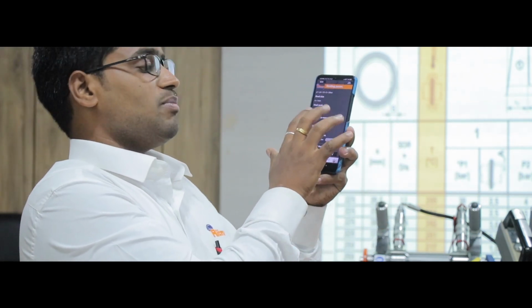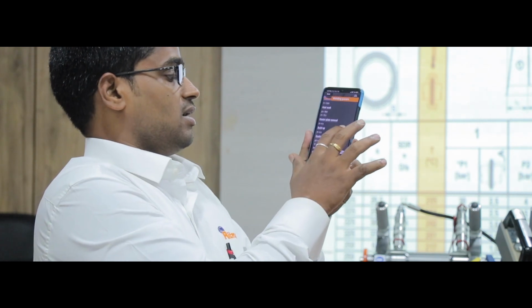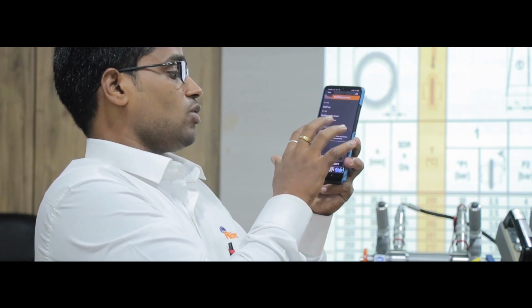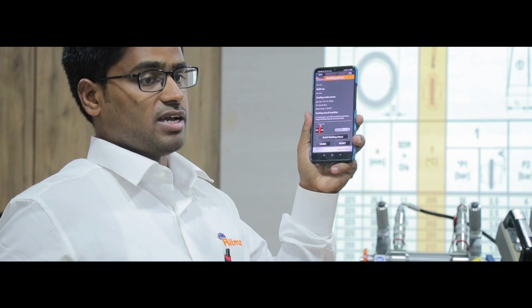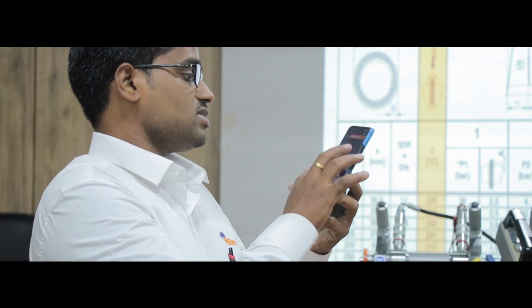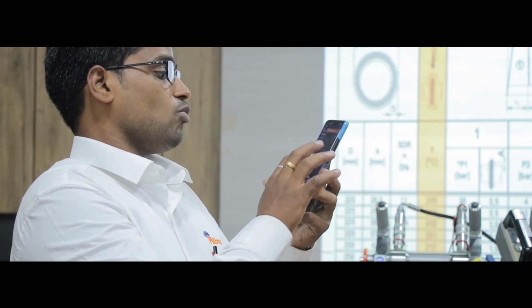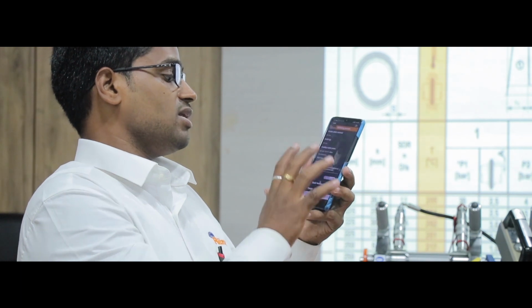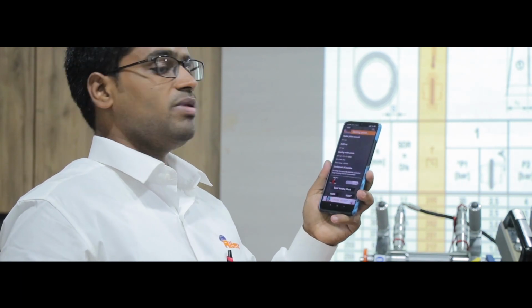Then the heat soak time is 72 seconds. And the total cooling time is 8 minutes 53 seconds. So 72 seconds is somewhere like 1.5 minutes, and this is 9 minutes. So the total welding time would be around 11 to 12 minutes for this pipe.